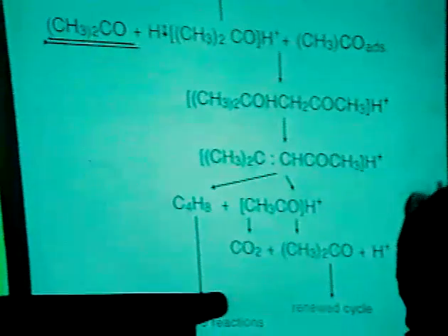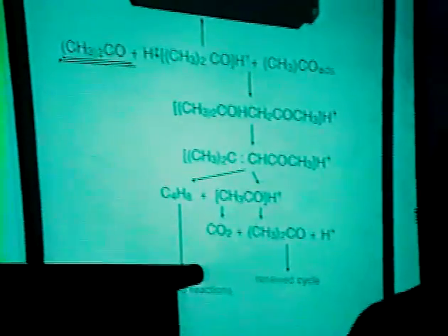But now the reaction route from this point differs from the organic homogeneous reactions, because this surface species is cracked to isobutene, as you can see here, and an acetate-like remainder, which is composed of CO2, again acetone, and the proton of the OH group is recovered.